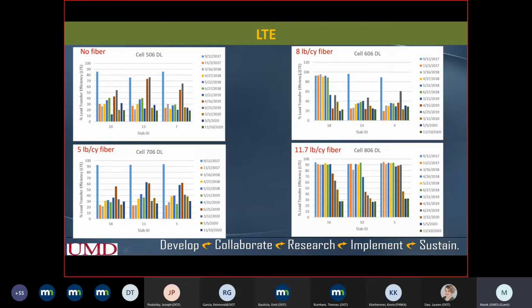When we looked at the load transfer efficiency with no fiber, we saw the load transfer in the very first test was really high, and then after that it really dropped. Now 606 and 706 had 5 pound and 8 pound fibers. Their behavior was not significantly different from the plain concrete. But cell 806, which had around 11.7 pound fiber, you can see with different dates, the load transfer did not decrease until about 1.8 million ESALs, and at 1.8 million ESALs the load transfer dropped significantly, not in almost all the joints, but one or two joints probably didn't show that much decline.